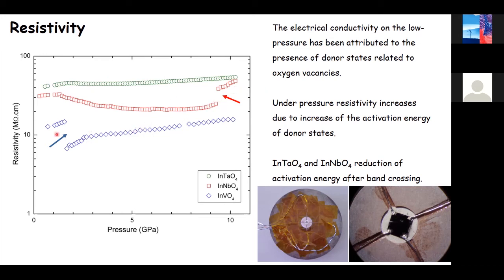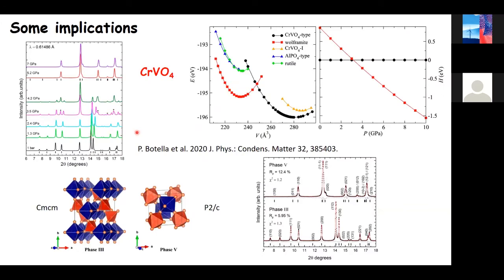The decrease here is not only due to the decrease of the band gap, but also because under pressure we induce defects by creating oxygen vacancies, which could behave as donor states, and that way the resistivity is decreasing because the free electron concentration increases with pressure. Okay, so these results also have implications in other compounds.